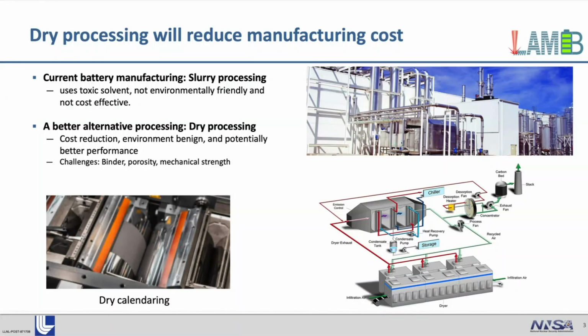So there's a trend to switch from the wet processing to dry processing to reduce the cost and also potentially improve the battery by enabling thick electrodes or customized structured electrodes for the high rate performance application. There are some dry calendaring approaches that have been developed in the industry, but they're still facing challenges like the choice of binders, the porosity control, mechanical strengths, etc.